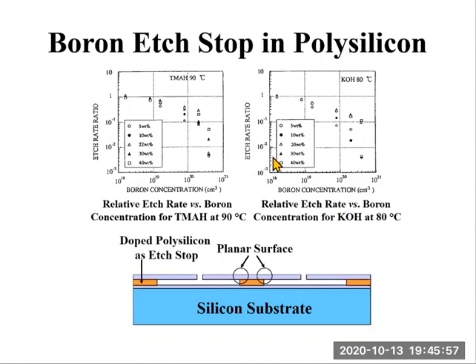Boron etch stop in polysilicon. Previously, we studied the boron etch stop in single crystal silicon. Now we can see that polysilicon also has the boron etch stop feature, which can be used to control the sacrificial etching. The left figure plots the relative etch rate of polysilicon versus the boron concentration for TMAH at 90 degrees C. We can observe that the etching rate can be reduced by 10 to 100 times by heavily doping polysilicon with boron. The horizontal axis is boron concentration.